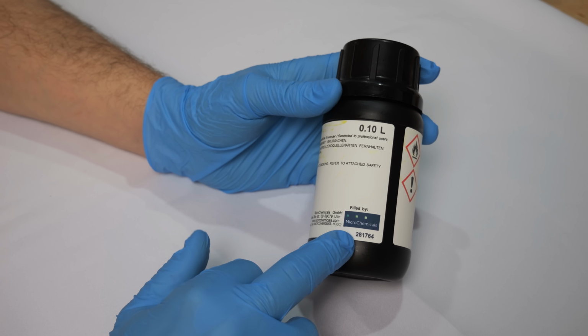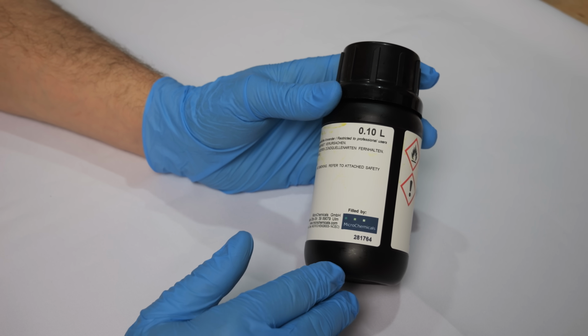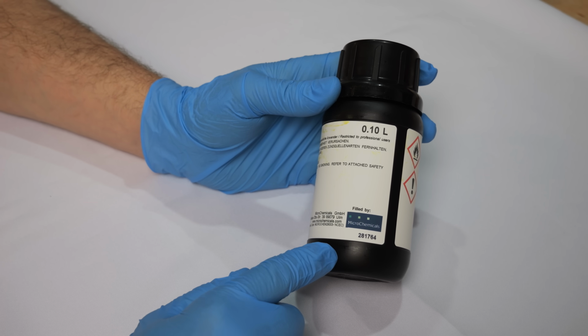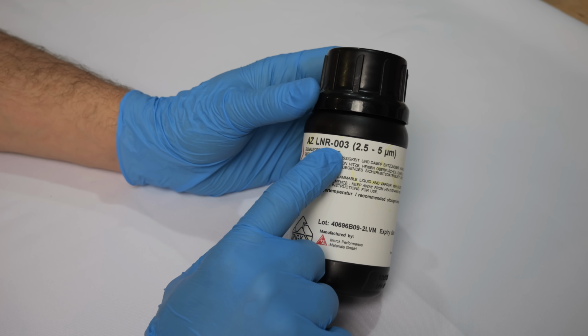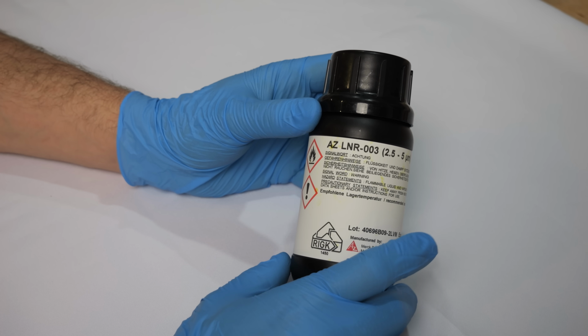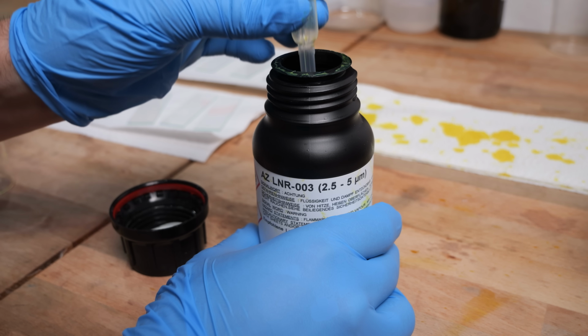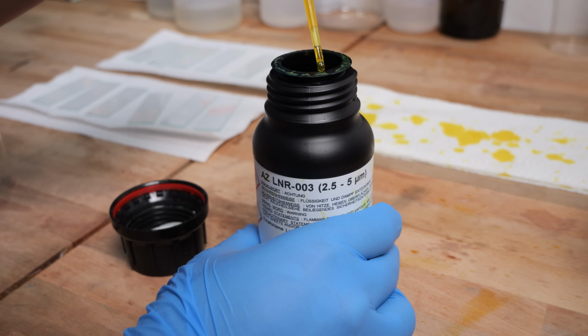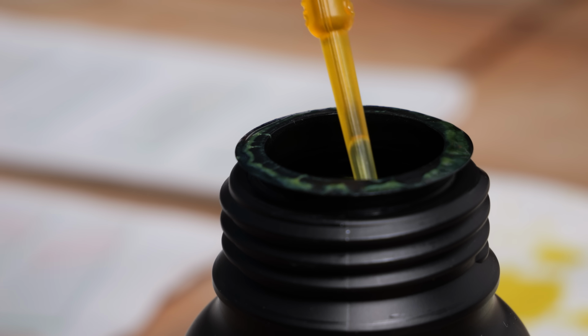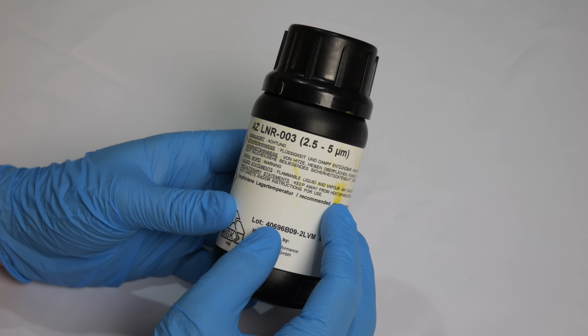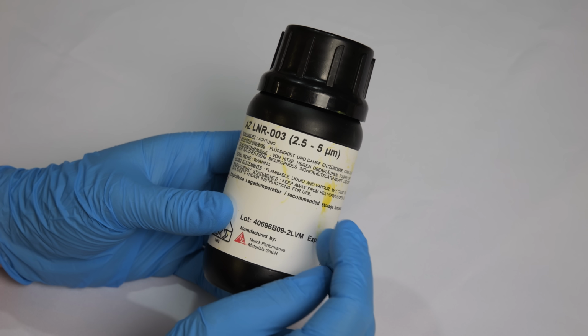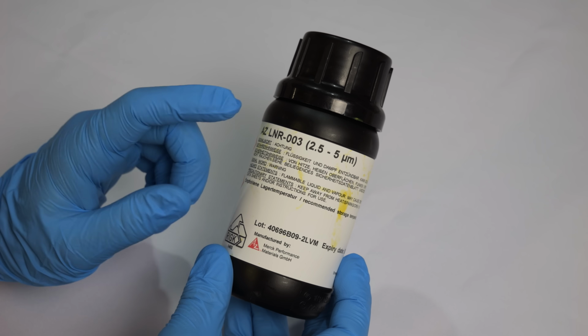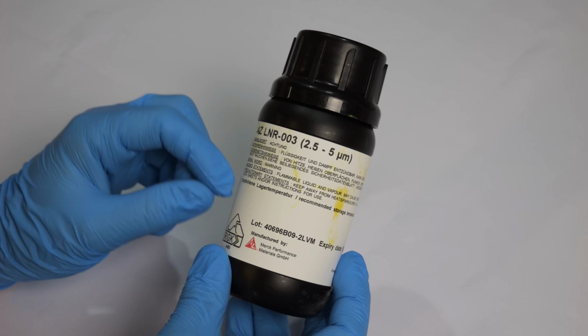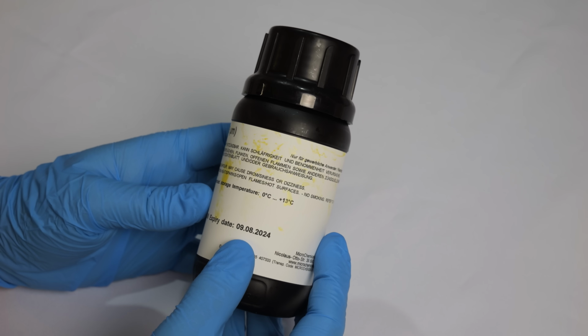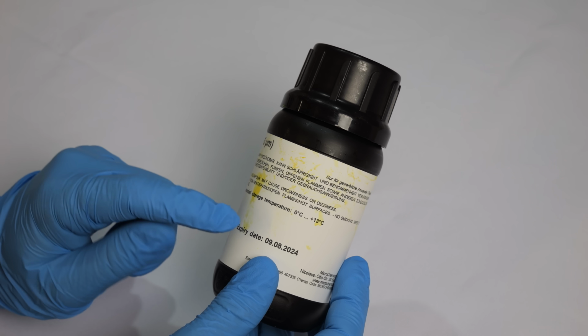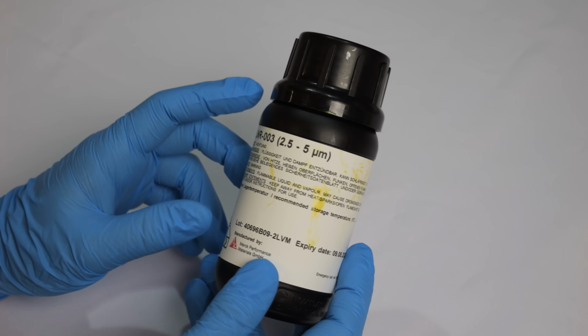In the end, I found a German company called Microchemicals, which sells a huge variety of different photochemicals. And this is the AZ LNR 003, which is specially meant for lift-off techniques. I honestly wasn't quite sure which photoresist to buy, so I chose the one which can be exposed with higher wavelength UV light and can be developed with a sodium hydroxide or potassium hydroxide solution. The only problem was that the resist was very expensive. Even with a 30% discount because the resist was about to expire, I still paid $170 for 100 milliliters.